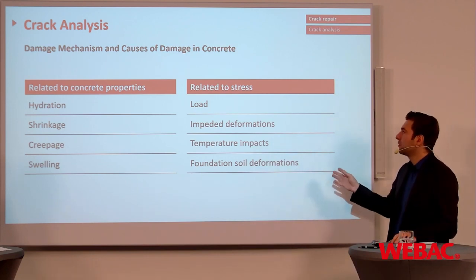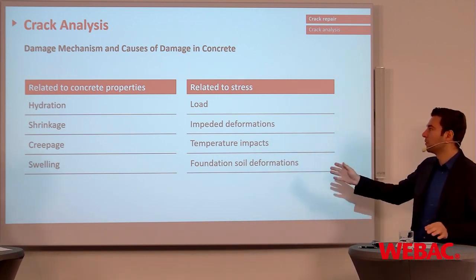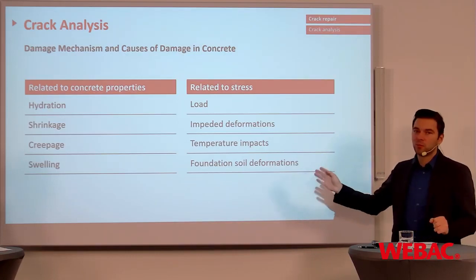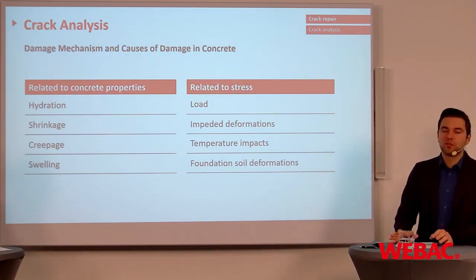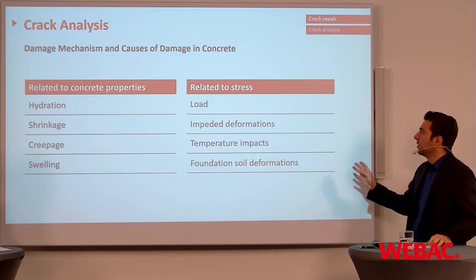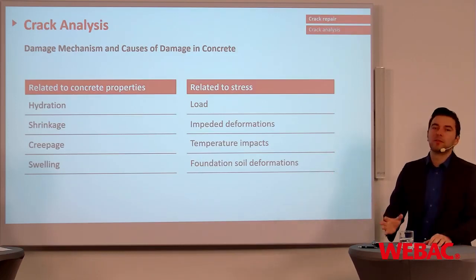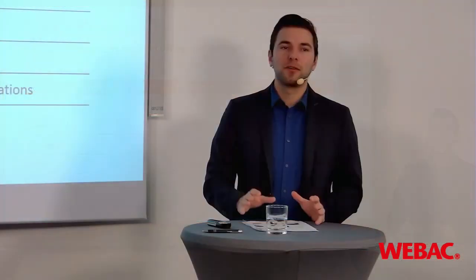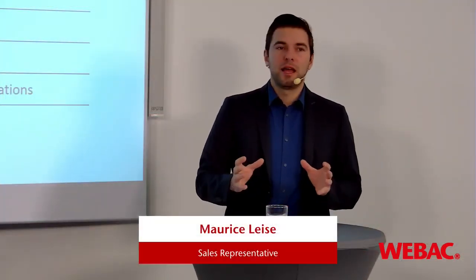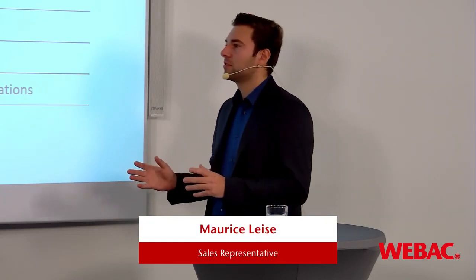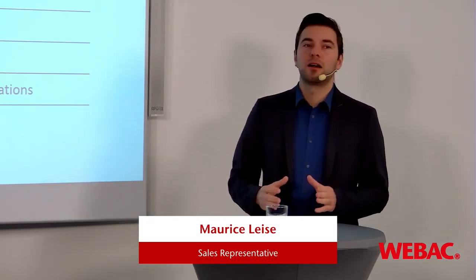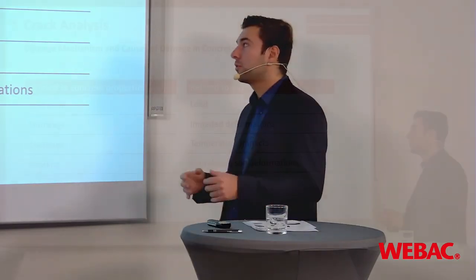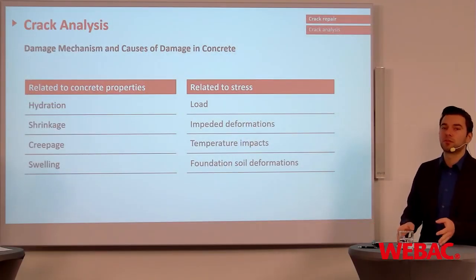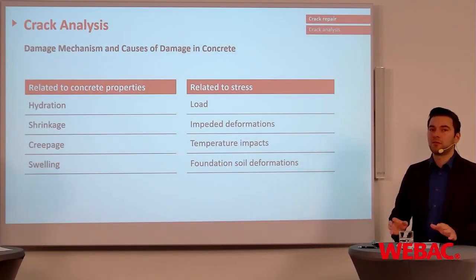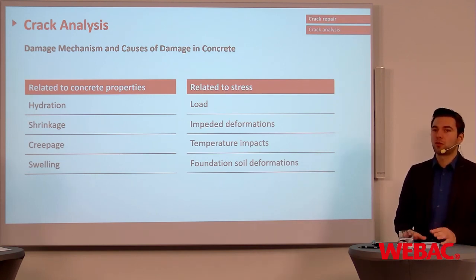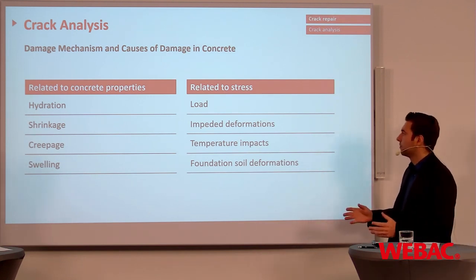The other ones are related to stress, and that can be loads, deformations, temperature impacts, or deformations of your soil. What does that mean? If your building, for example, was designed for loads with forklifts of 5 tons, and after some time you see that there is a change, that the forklifts are 10 tons or 15 tons, for sure, this is also going to have an influence on your structure, on your concrete. So therefore, unexpected loads on the concrete can cause cracks.